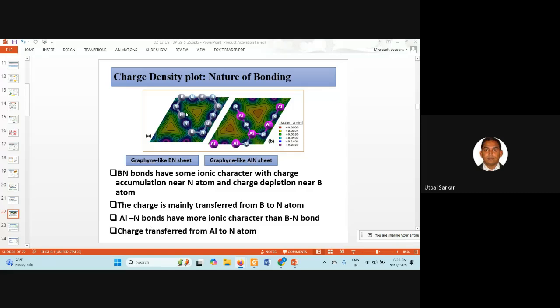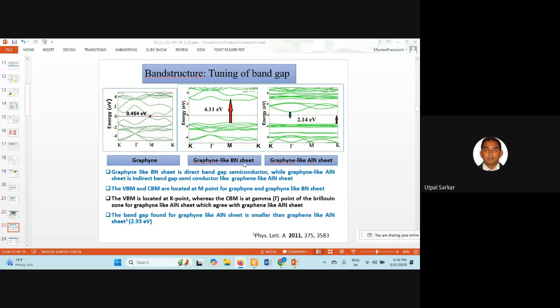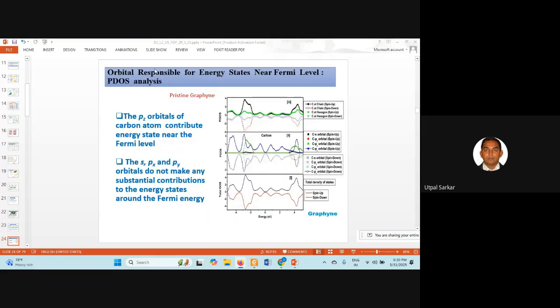You see here the depletion of electrons around aluminum and boron. If you compare, here a little bit of electrons are situated, but here no. So aluminum nitride bonds have more ionic character than the BN bond, and charge is transferred from aluminum to nitrogen. How this charge rearrangement is occurring within the bonds, you can also quantify here. These are the band gaps for aluminum nitride sheets, so if you are interested, have a look at it. And this PDOS we have already discussed, so the same thing here, but for this particular structure.